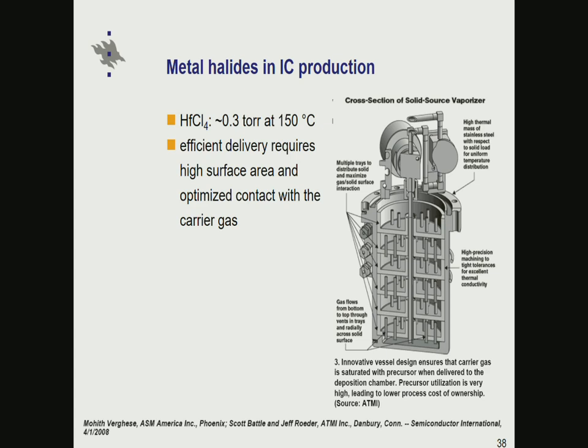Okay, so Christoph also said that in 2007 ALD went into production in a much larger application. That's true, in high-k gate oxide. But what he didn't mention, because he was not talking about precursors, is that there the precursor is also a metal halide. It's hafnium tetrachloride, which forms the core of the chemistry that Intel started using there. It was not a trivial thing, because hafnium chloride is reasonably difficult to evaporate. The vapor pressure is 0.3 torr at 150 centigrade.